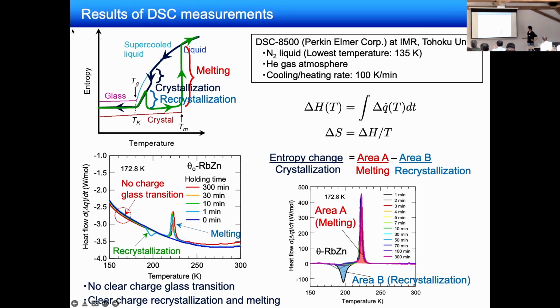As you can see, there are anomalies related to recrystallization and melting, but we couldn't observe any glass transition. So the entropy change at the glass transition may be very small to detect in the DSC measurements. Anyway, we subtracted the baseline from the raw data, and we got this very nice result. The entropy change related to the crystallization can be calculated by subtracting area B from area A. Then we obtain the entropy change related to the crystallization.